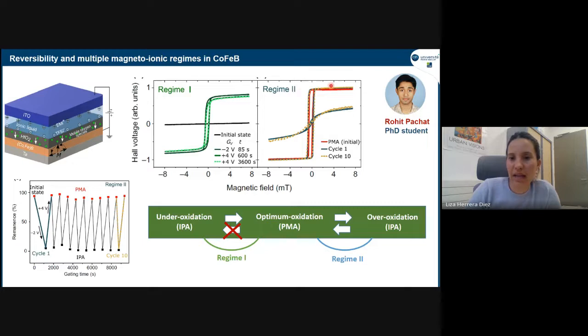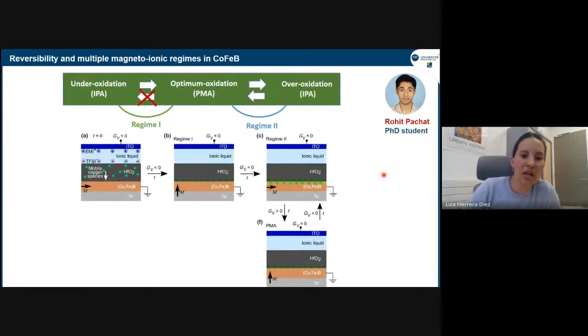It goes this way, but it doesn't go back. However, the second state, PMA to over-oxidation, which goes back into the plane, was perfectly reversible. And here, for example, we could cycle it many, many times, and it was going back and forth very nicely. So once again, we understand more and more that these two regimes are really not quite the same. So this is really our interpretation of what is going on.